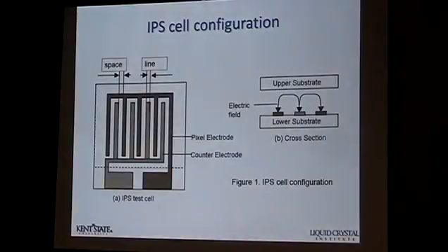So in the cells used for this study, as we say, we need to optimize this effect of the cell gap, and also the pitch of the electrodes. Certainly, the width of the electrodes is also very important. But for a lab study, it doesn't matter. For industrial manufacturing, since they have in-plane switching, trying to eliminate this disclination line and light leakage to give you a wide viewing angle, the zigzag electrodes are used instead of straight ones.